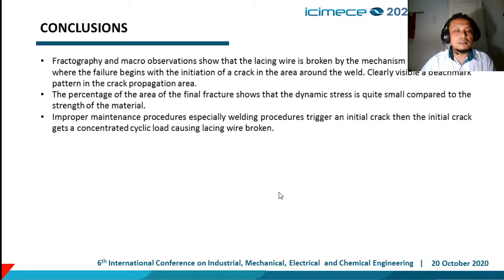So we can conclude from fractography and macro observation that the lacing wire is broken by the mechanism of fatigue failure, where the failure begins with the initiation of a crack in the area around the weld. A beachmark pattern is clearly visible in the crack propagation area. The percentage of the area of final fracture shows that the dynamic stress is quite small compared to the strength of the material.